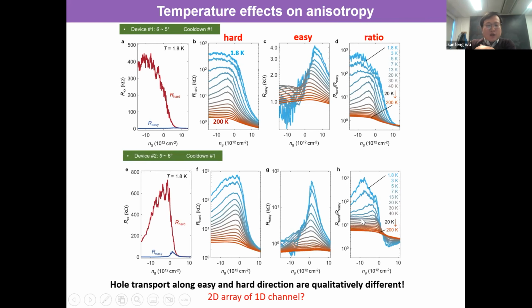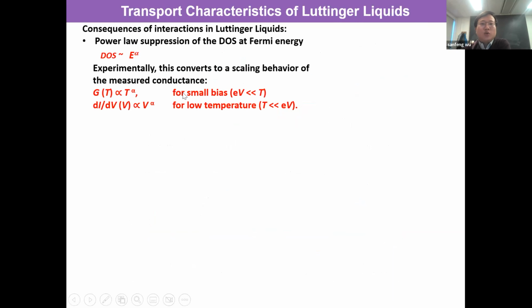So the question is, what's going on in the material, why do you have such strong anisotropy on the hole side, and why is the transport so qualitatively different? Do you have a 2D array of one-dimensional channels, right? That's what we want to study. And the most important question will be, is there Luttinger liquid physics in this system? As I mentioned, there are two important aspects of a Luttinger liquid. One is the power law suppression of density of states. The other one is spin charge separation. So far we don't have any evidence of spin charge separation, which I think is a very interesting or exciting direction to explore in the future. We can, however, reveal the power law suppression of density of states.